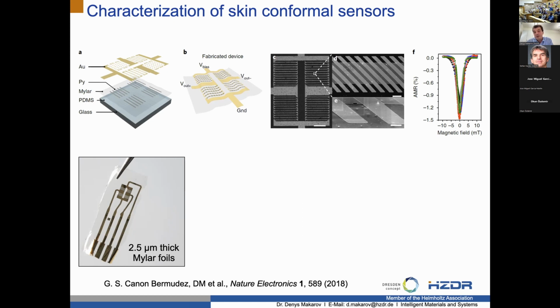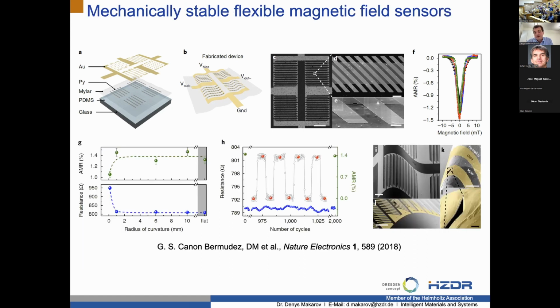They are prepared on, let's say, very thin polymeric foils, and therefore a large majority of our work is dedicated to understanding also the mechanical stability of the sensors. When does the resistance become changing, for example, when you bend your sensor, when the magnetoresistance starts changing when you bend your sensor, or you start to do such kind of repetitive bending test where you simply bend your sensor many times to predefined bending radii, and you see what is actually happening.